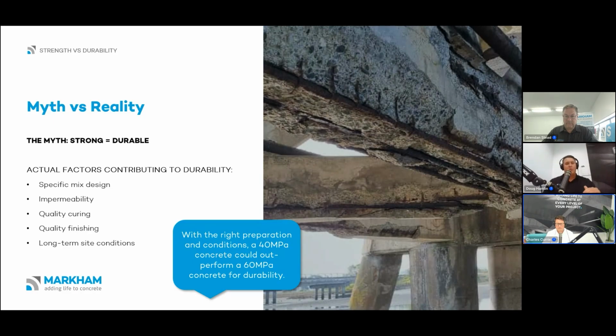But therein lies the problem, in that the higher the MPa doesn't mean higher durability in the concrete. So there's things like specific mix design. You could be having a lower MPa concrete, say a 40 MPa concrete, with the right conditions, right mix design, that could actually outperform a higher MPa concrete. Now, this is not a complete blanket statement, but it's very true of many construction sites, because they're not doing quality curing on site. They maybe not doing quality finishing. The long-term site environment is not being considered. And most importantly, the impermeability is not being considered.